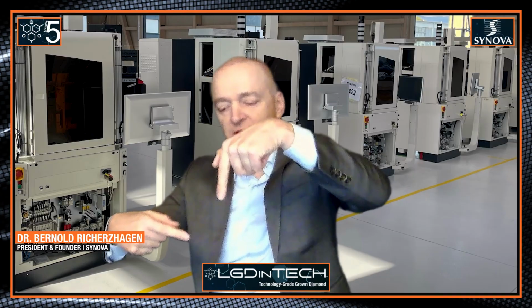And now you can also imagine that if you cut from both sides, for example, you have a cylindrical workpiece and you rotate it and you keep your laser water jet from the top, we only have to cut the radius. So at the end we can cut twice that depth of 50 millimeters. We have been able to show that it works in silicon, also silicon carbide, which is another very hard material. Not as hard as diamond, but also very hard, very difficult to slice.